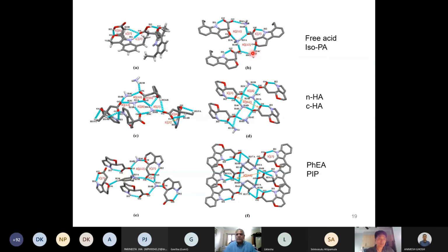So there is also an enthalpic factor when you are going from the single molecule crystal structure to the co-crystal or the salt structure. And here the counter ion is an ammonium species, or an alkyl ammonium species to be precise. So this is the isopropylamine. I'm not putting the R group of the amine just to make the structure clearer. You see that the carboxylate anion sits in the middle, and it's hydrogen bonded to the large number of oxygens which are present in the drug molecule.